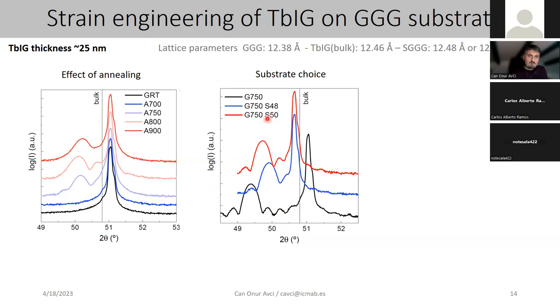But also, to our surprise, we tried different GGG substrates with different lattice parameters. In a standard GGG, we have this lattice parameter, 12.38. In the bulk film, we have 12.46. So that's why we get the strain. But we got a strained state even with other types of GGG, which are non-standard and have larger lattice parameters. So that was to our surprise. But this means that we can get PMA basically on all kinds of GGG substrates.